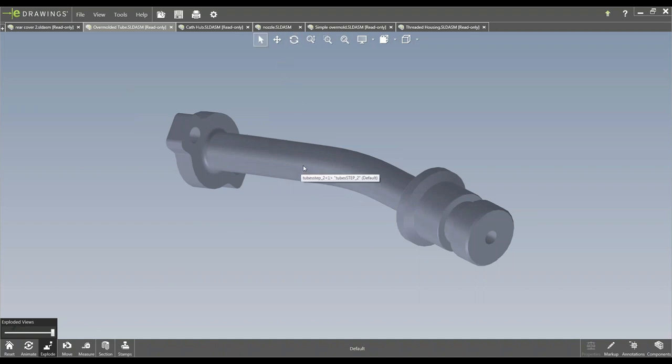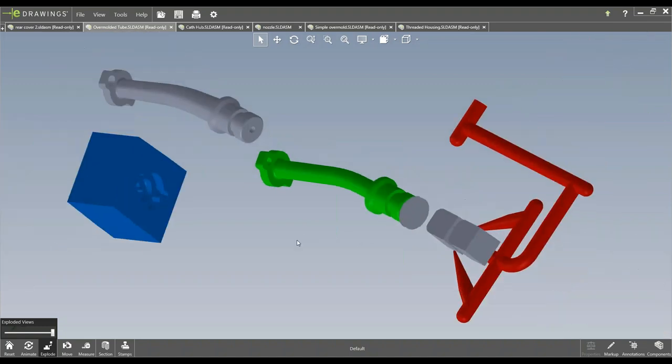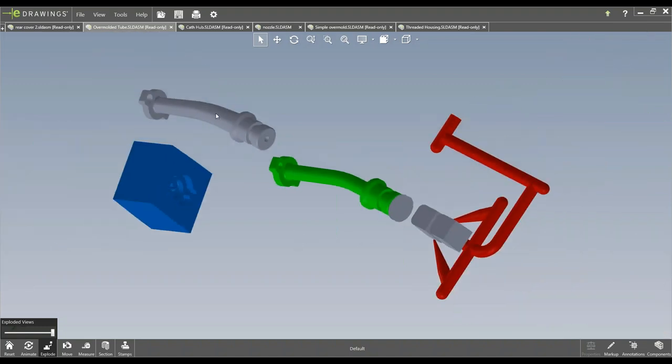Where it moves in here during the injection process, it may float and move to this edge or this inside edge, depending on the material's filling. So the customer couldn't have any exposed tubing, so the solve was to overmold the jacket around that. So if there was any thin wall or any thin wall...